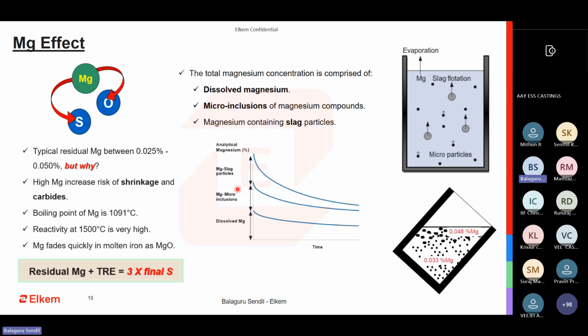To achieve most of the magnesium in the micro inclusion category, you should use an extremely low grade of FSM with low magnesium. You need not go for higher FSM or higher treatment processes. Then it is very difficult to actually get a residual Mg that is representative of what is there inside. So do we really need a minimum of 0.030? That is the question. It doesn't always need to be 0.030. It needs to be correlated to the sulfur you have, and also to the subsequent inoculation that you're going to do.